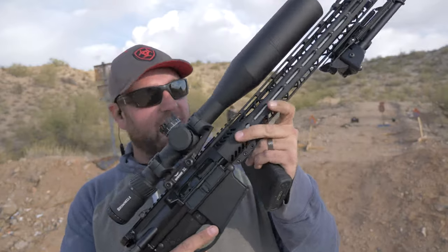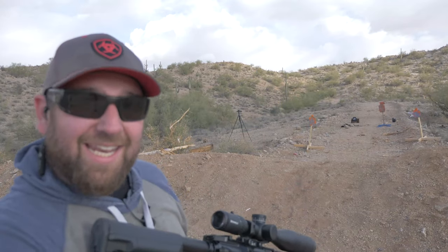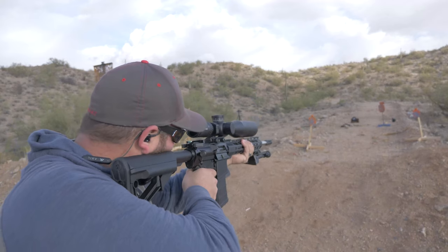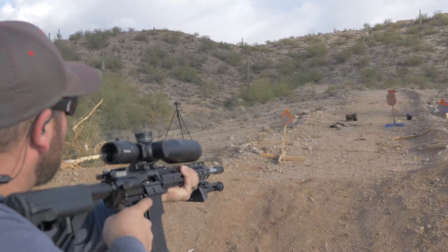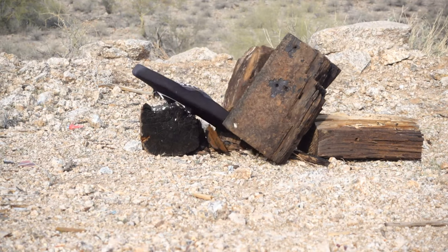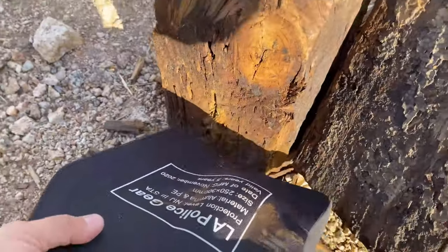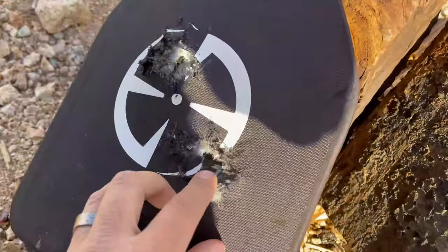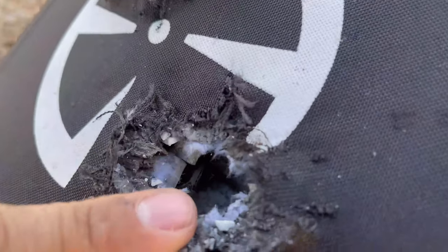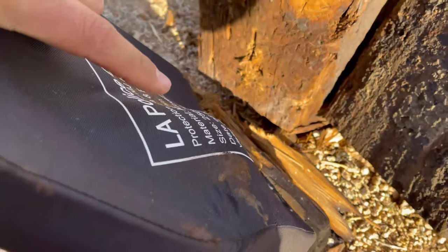What we're going to hit it with next is Tactical Toolbox John's .308 AR-10 — one round of standard full metal jacket .308. Well, it definitely stopped it. We got a pretty heavy deformation — this would have broken some ribs, I think. You can see the front where it goes in, the ceramic on the side, and then it's all fibers inside. Yes, it did stop a .308, which is impressive because that is one hell of a bulge right there.